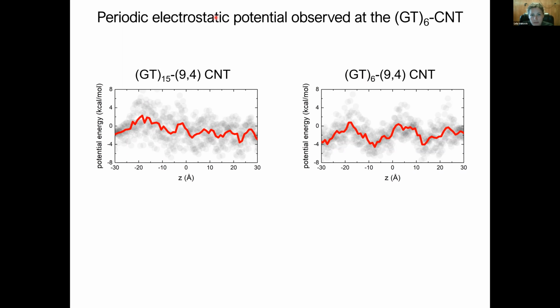And the electrostatic potential at the nanotube surfaces, due to the DNAs wrapping them, turned out to be kind of random potentials. You see, there is no pattern here that we observed for the long DNAs. But when it came to GT6 DNAs, these rings, the electrostatic potential in which this exciton was living turned out to be periodic. So you can see here, we tracked the electrostatic potential along the nanotube length. And when you have the rings there, the electrostatic potential was periodic. That's the potential in which the exciton existed and it needed to relax back.